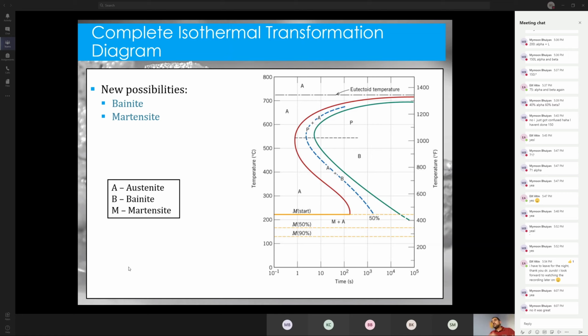Now, if we look at even lower temperatures, we find that the curve, as we discussed before, up until here, the transformation is happening faster and faster. And I know that because look up here, it took 10 seconds for the transformation to begin. Around here, it's only 1 second. But if I keep decreasing the temperature, the times begin to increase. So at 400 degrees, the time has become almost 5 seconds. At 350, it's 10 seconds. At 280, it's 100 seconds. The time is getting longer and longer. So that's similar to what we talked about before.